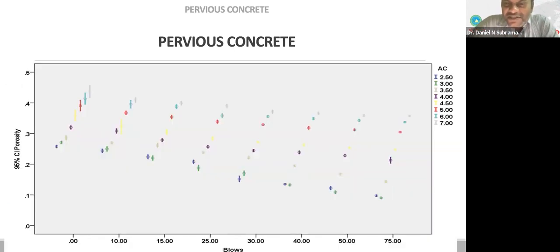Okay, now we'll go into our data. So this is giving us the data that we obtained. The x-axis has the number of blows, that is the compaction. We compacted our samples with the standard Proctor hammer, which is 2.5 kilograms dropped from a height of 300 millimeters. So this gives how many blows we gave, 10, 15, 25, 30, when we were casting the cube. And on the y-axis, you have the porosity. Each color gives us the aggregate to cement ratio.